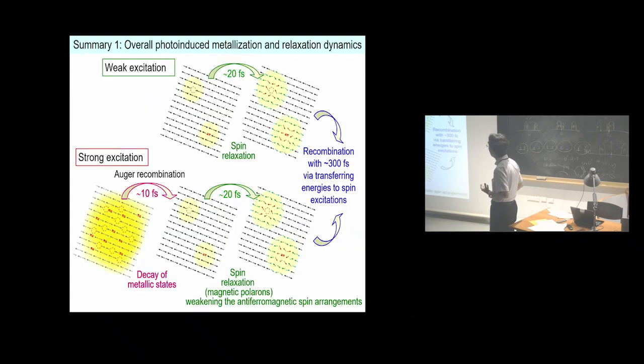Okay, this is the overall photoinduced metallization and relaxation dynamics. By the weak excitation, the metallic state is hardly observed. By the strong excitation, the metallic state is formed, but it decays very fast via the doublon-holon recombination processes, and the residual doublons and holons are relaxed as magnetic polarons via the weakening of the antiferromagnetic spin arrangement like this. And finally, they recombine with 300 femtoseconds via transferring energies to spin excitations.